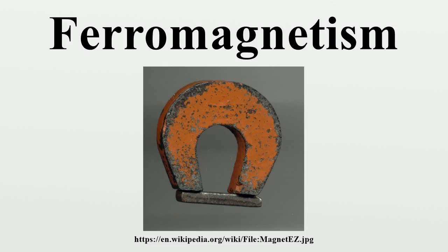This is shown by the Barkhausen effect. As the magnetizing field is changed, the magnetization changes in thousands of tiny discontinuous jumps as the domain walls suddenly snap past defects. This magnetization as a function of the external field is described by a hysteresis curve. Although this state of aligned domains found in a piece of magnetized ferromagnetic material is not a minimal energy configuration, it is metastable. Heating and then cooling a magnetized material, subjecting it to vibration by hammering it, or applying a rapidly oscillating magnetic field from a degaussing coil tends to release the domain walls from their pinned state, and the domain boundaries tend to move back to a lower energy configuration with less external magnetic field, thus demagnetizing the material.